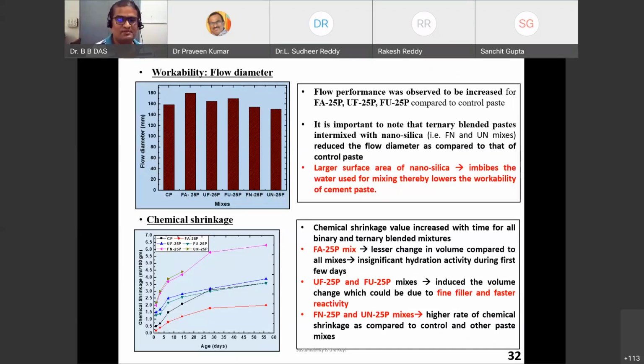Here the percentage was very, very small, that is 2%, so we didn't require a superplasticizer. But the moment it goes to 3%, we have seen it is impossible to work without a superplasticizer for a nanoparticle, nano silica admixed cementitious composite. So this is basically your workability, and this is your chemical shrinkage. Now let us go one by one.